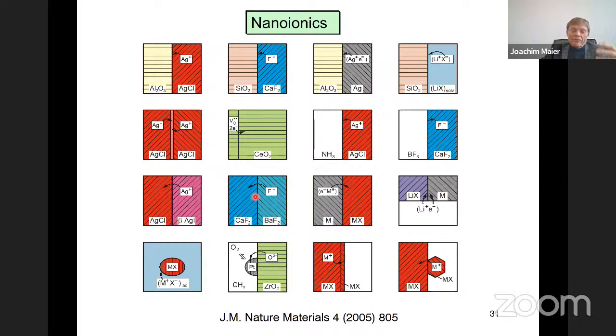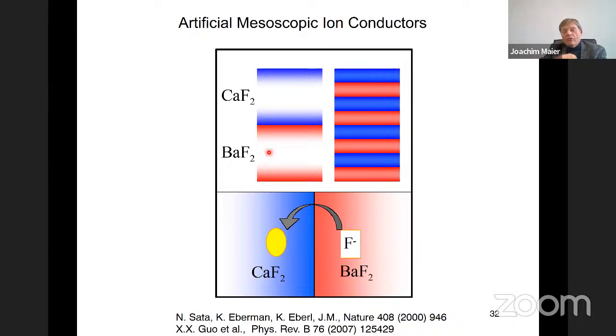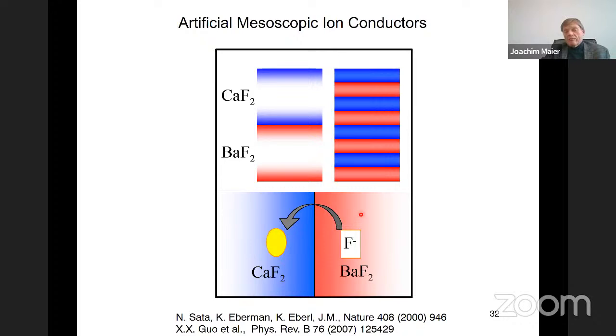We have identified a whole zoo of examples — referring to electrolytes, electrodes, sensors, storage situations, and more. One well-known example is heterolayers of two fluoride ion conductors: the conductivity behavior of multi-layers made by molecular beam epitaxy is solely determined by the redistribution of fluoride from the BaF₂ space charge zone into the CaF₂ space charge zone. This is now extremely well understood; a summary of at least 10 years of work is available in the second cited reference.